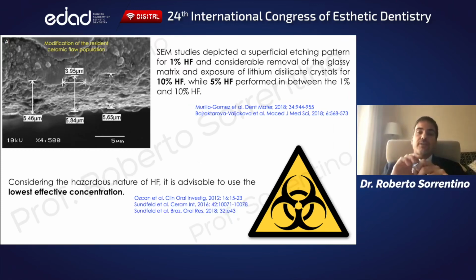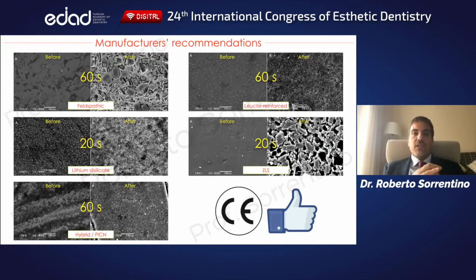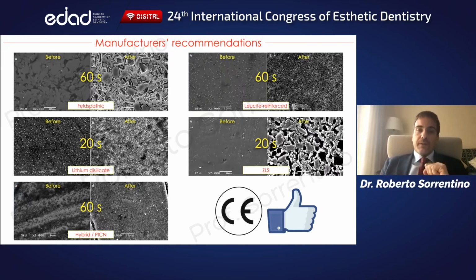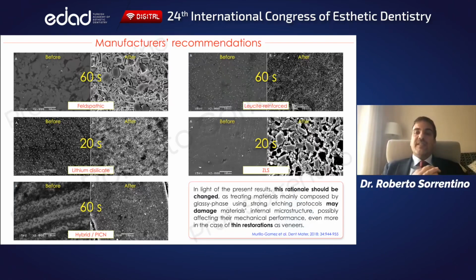According to manufacturers' instructions, recommended etching times change on the basis of the glassy content. In other words, the higher the silica percentage, the more aggressive the etching protocol. As a consequence, we should etch purely glassy materials such as feldspathic and leucite reinforced ceramics for 60 seconds, silica-based substrates for 20 seconds, and hybrid ceramics, just like the newer polymer infiltrated ceramic networks, for 60 seconds as well. However, in order to preserve the ceramic microstructure, strong etching protocols should always be avoided, particularly in the presence of very thin restorations, just like laminate veneers and tabletops.